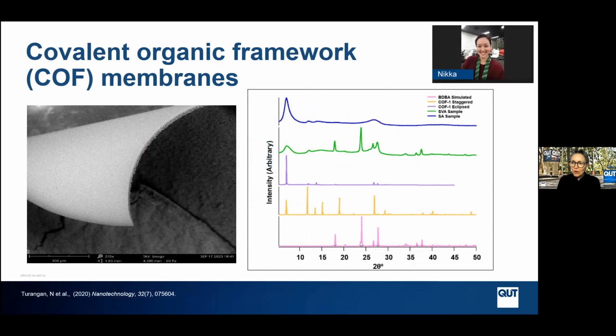So we've been looking at these not just in the monolayers that I showed you, but also trying to propagate that layer thickness upwards. And this is Nika, who is a PhD student who's been engaged in this work. We initially started out in Nika's project looking to make very sort of moderate thickness layers, which of course for a surface scientist meant we were going for about 10 layers or so. But we quickly figured out it was much easier to study them when we made them thicker.